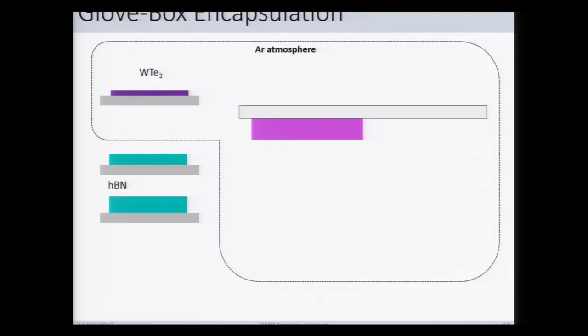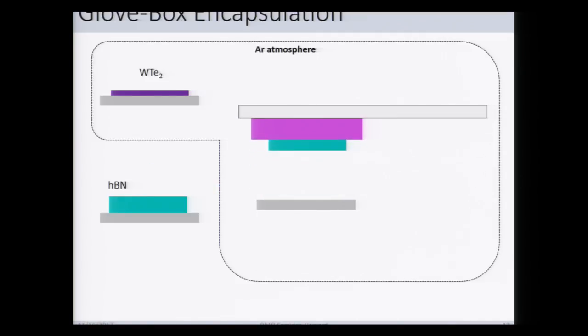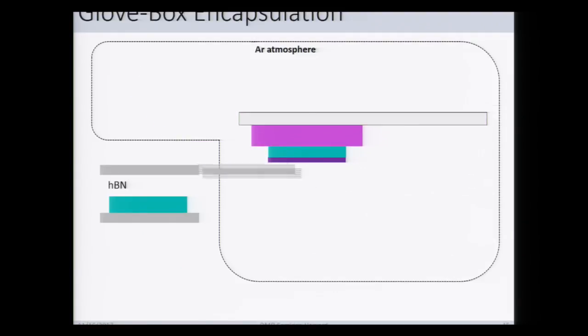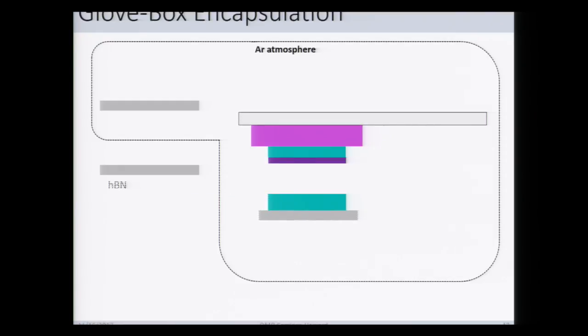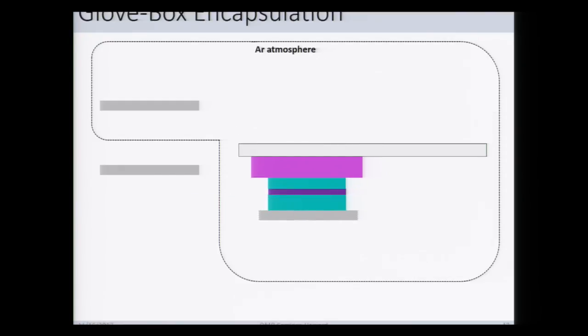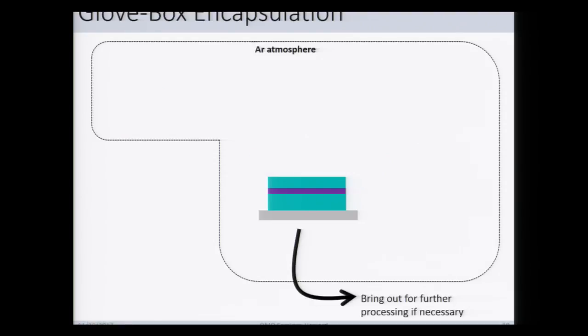So we have the argon atmosphere inside this dashed line. Boron nitride we can exfoliate and characterize outside of the glove box just because it's air stable. And then the tungsten telluride we exfoliate and inspect in the box before doing any fabrication. Here we have our glass slide and our sticky polymer, and we bring our boron nitride inside and pick that up first. This very clean bottom surface of the boron nitride is then used to pick up and protect the top surface of the tungsten telluride. And then finally, for example, we can come down and encapsulate it on both sides with boron nitride like that. We can remove the stacking procedure materials, and then, if we want to, take it outside of the box for further processing.